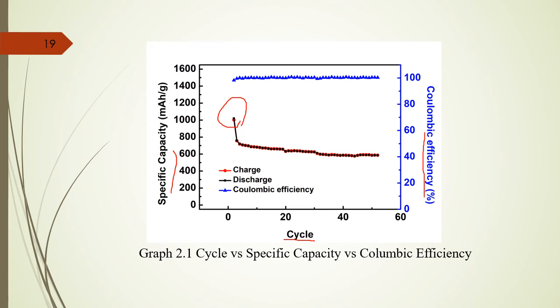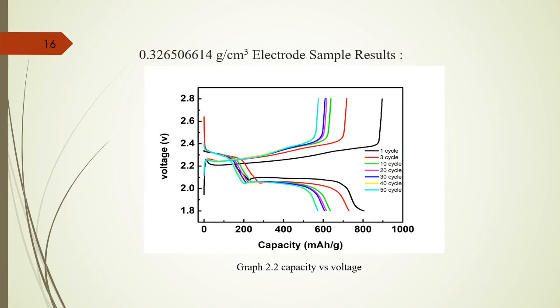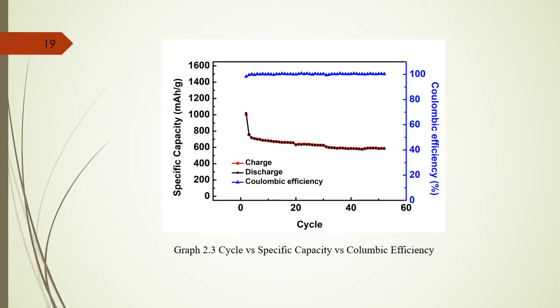Let's see the results of the second battery. So here is the second battery result. The loading of this sample is even less than the first sample. So here are the results. This is also almost 1000, but a little less than the first one. This is because here I use very low loading for this sample, so I have achieved less. So let's see the cyclic stability of this sample as well. So here is the stability, almost the same, but with a little bit of difference in the Coulombic efficiency as well as the cyclic stability. So these are the two samples.